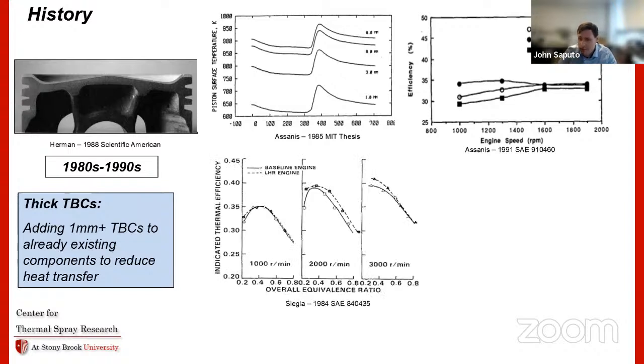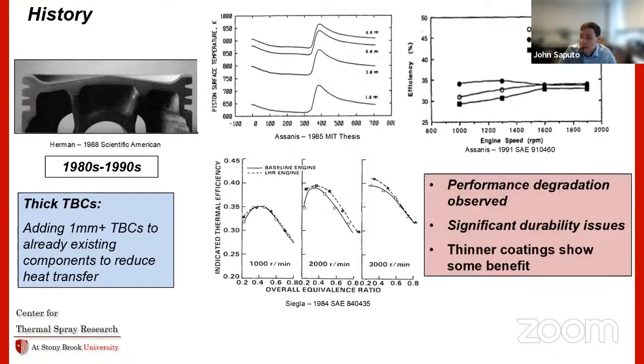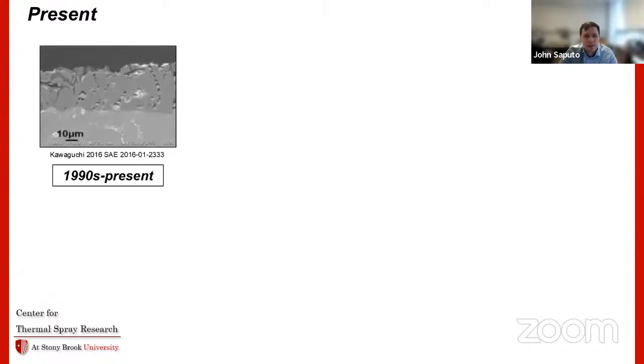And so it's interesting, there were theoretical predictions about this made as early as the mid 80s, where people were showing that these thinner ceramic coatings, as you move to higher frequencies, could possibly perform better. So overall, this period in time can be summarized by degraded performance from thick ceramics. The potential to use thin coatings has some benefit. And because people were using these thick brittle ceramics, there were some pretty severe durability issues. So that leads you into the present state of thinking in this field.